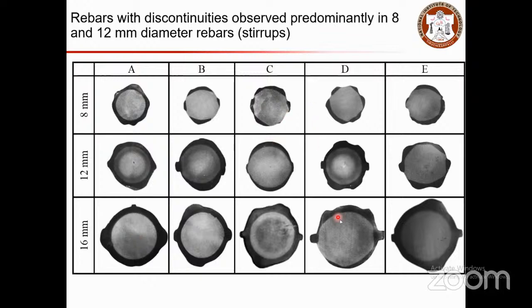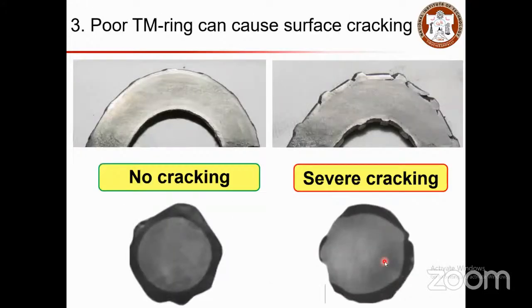That is because awareness has not reached well enough to ensure that the phase should be in this range and the TM ring should be in this range. One intrinsic fact is that this is more irregular when the diameter of the rebar is smaller. As the diameter increases, this is controlled a bit better. Other than that, for these TM bars we need to do a surface cracking check. We have to bend the bar and see if there is any cracking on the surface or not. We bent the bars like this. You can see the cross section here. This is a good cross-sectional bar.